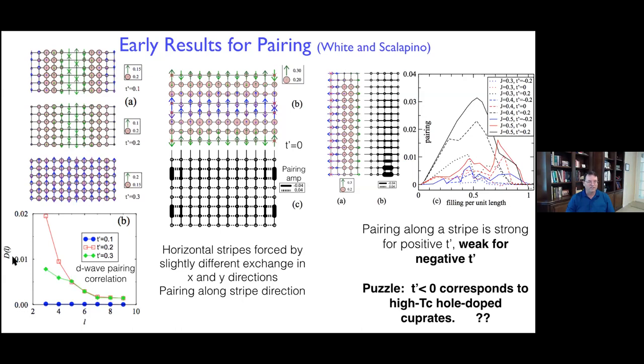And you might think that the numerical value 0.01 is rather small. You shouldn't think that, because the operators that we can make to create a pair only have a modest overlap with the actual structure of a pair. So you get a constant factor that reduces it quite a bit, and so we're really looking more at the decay. You get a big response for this positive T prime. And if you look at how that corresponds to the striping up here, it looks like if you have stripes that are too strong, you get no pairing. Stripes can still be there, but if they're a little bit broader and more spread out, you can get pairing.